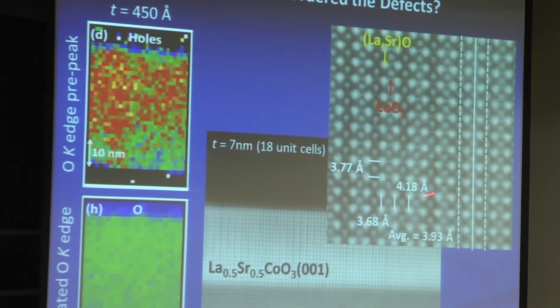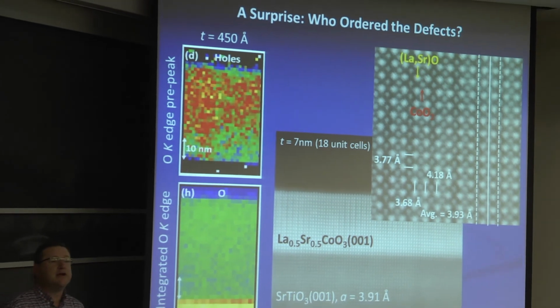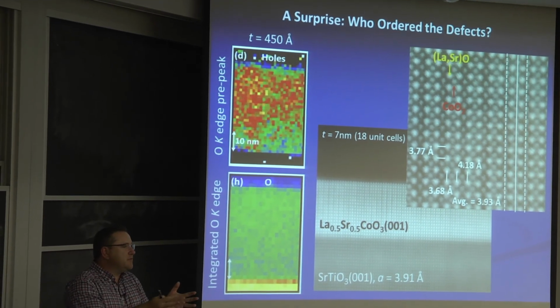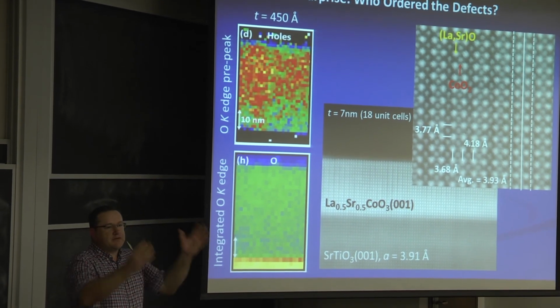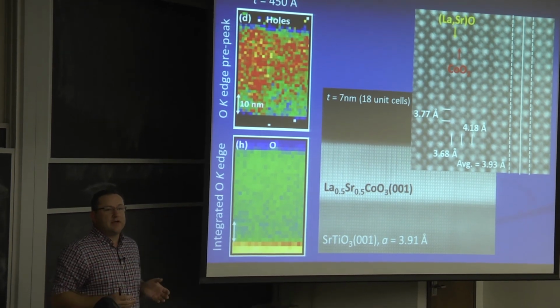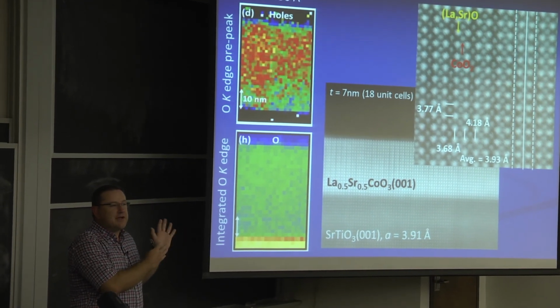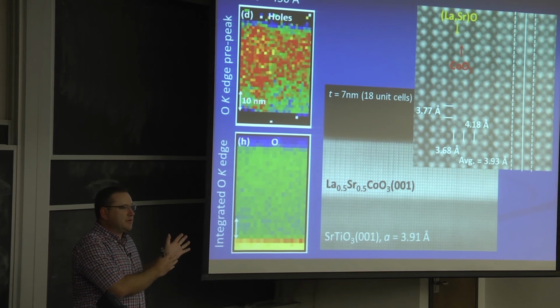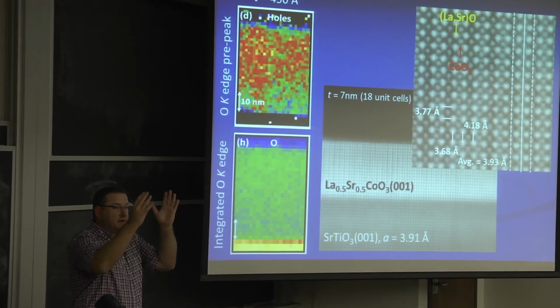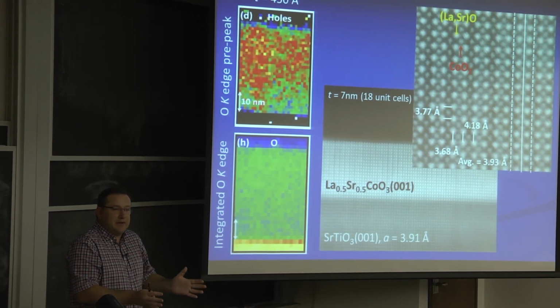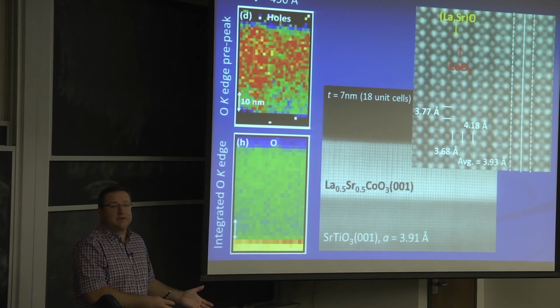I get this because what the material has done is really smart, right? The way it normally makes up its mismatch with the substrate is you put in dislocations at a massive energy cost. This thing figured out, okay, if I can form oxygen vacancies at a much smaller energy cost and I can line them up into stripes so that I can expand my in-plane lattice parameter, I can exactly match the substrate, right?